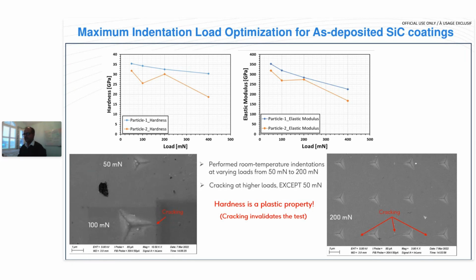We performed room temperature indentations with varying load from 50 millinewtons to 200 millinewtons. And on the top that you see is the hardness versus load response on the left. At 50 millinewtons load, there were two different particles that we used. The hardness was 30 plus GPa, 35 and 32, 33 GPa at 50 millinewtons, but hardness did drop with increasing